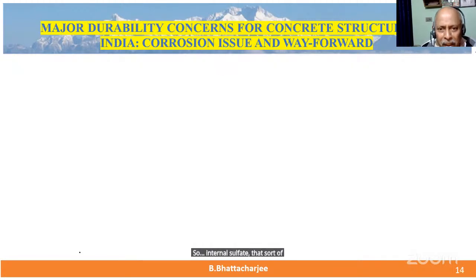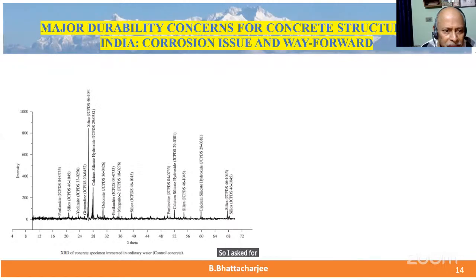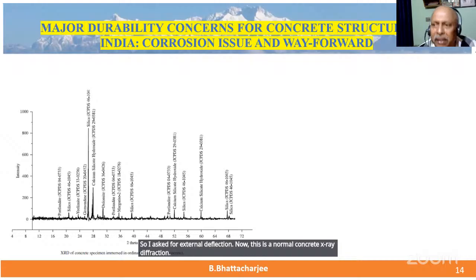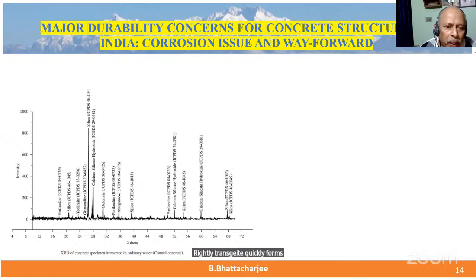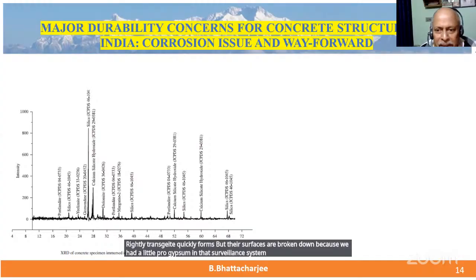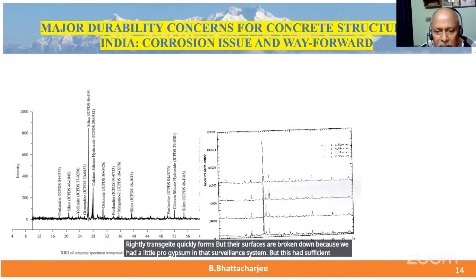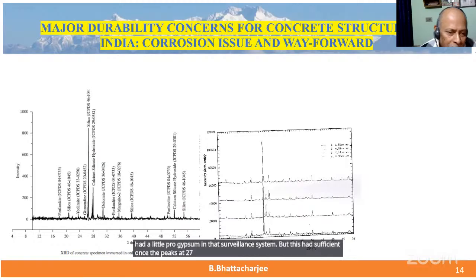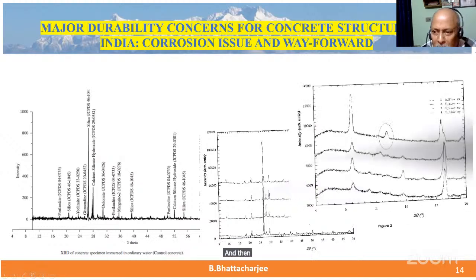I had to prove it. So I asked for X-ray diffraction. Now this is the normal concrete X-ray diffraction, which doesn't have ettringite. Ettringite is the product from sulfate reaction, right? Ettringite quickly forms, but their surfaces are broken down because we had a little bit of gypsum in the cement system. But this had sufficient ones. The peaks at 27 represent ettringite, which was not there in normal concrete, as you can see in the left-hand bar. And then I took some more detail.